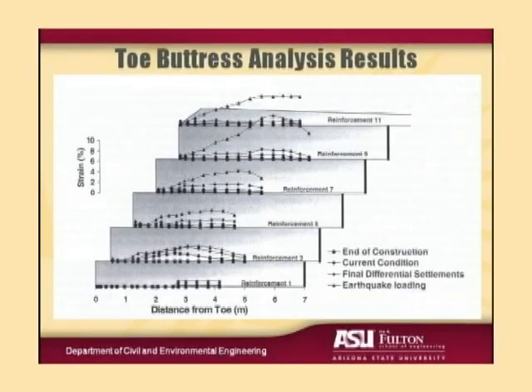Well, this slide summarizes the deformations from our analysis. We built up the geogrid, we built up the toe buttress in sections, so we were predicting strains at the end of construction. We had the current condition for the current measured settlement, the final differential settlements after we put that 7.5 feet of differential displacement on it, and then the earthquake loading.